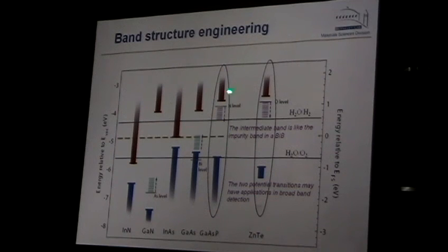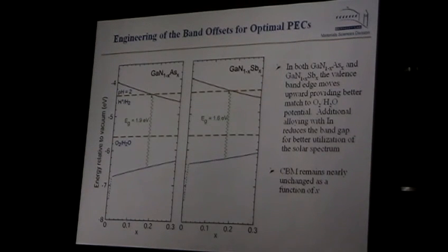In this case, gallium arsenide phosphide by pushing this nitrogen level down, and zinc telluride by pushing the oxygen level down. So the gallium arsenide nitride system is another interesting possibility. Now we could add, as I said, we would like to have gallium nitride with antimony. We were able to produce gallium nitride with arsenic, so we pushed the valence band up. But still, we are not close enough, because when we want to add indium to this, the conduction band goes down and eventually falls below the redox potential, and we don't want this to happen.